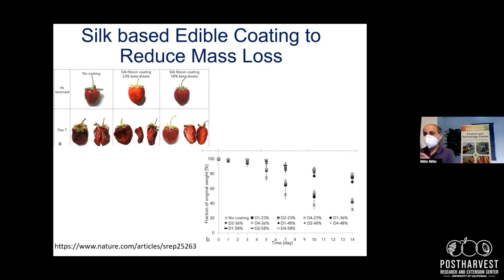during storage. And what they showed was that without the coating, they lost about 70% of the mass in about 12 to 14 days. And using the silk fibers as a coating material, depending on the beta sheet content, they were able to reduce the loss by more than 50%. So it illustrates the application: using a biopolymer derived from an insect, in this case, we are able to provide a protective coating that reduces mass loss on the produce surface itself. And I like this study because it's very demonstrative in terms of the quality of the sample that has gone through it and illustrates the application very clearly.